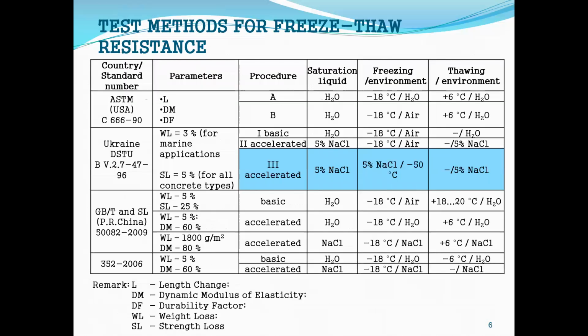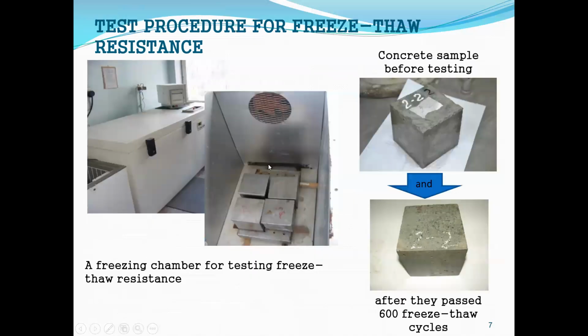Freeze-thaw resistance of alkali-activated blast furnace cement concrete was studied according to the third accelerated test method prescribed by the national standard of Ukraine. According to this accelerated method, the concrete cubes were saturated with a 5% solution of sodium chloride at temperature 18 degrees, and after that were subjected to freezing at temperature minus 50 degrees. Thawing was done in a 5% solution of sodium chloride.